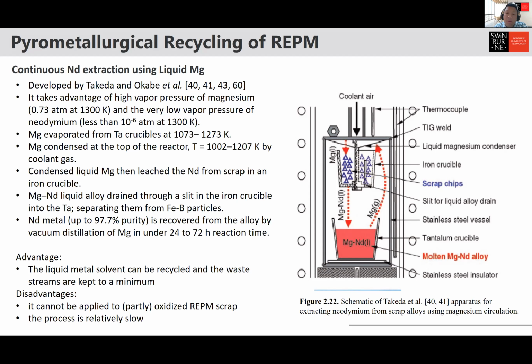Now the problem is if you have oxides, then the magnesium cannot really penetrate through and react with the neodymium. So it cannot be used when you have a REPM that is heavily oxidized. And the process is also relatively slow. The fact that the process is quite slow means that we need to provide the heating for a long time. So the heating cost will be quite high.